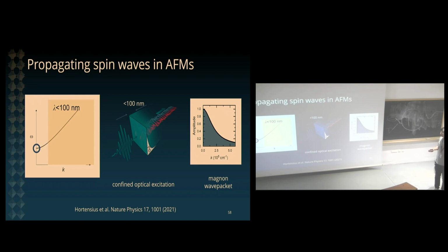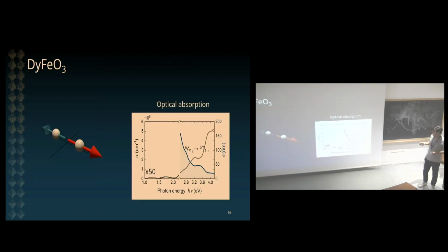So the idea is, can we scan our materials and find an optical resonance with a penetration depth of, let's say, 50 nanometers or below? We know that the wavelength of the spin waves that we study is typically in the hundreds of nanometers range. So if you can find an optical resonance that is 50 nanometers or below, then there's a possibility of really exciting a wave packet that has a certain number of Fourier components, and this can realize a propagating spin wave. So that was the idea.